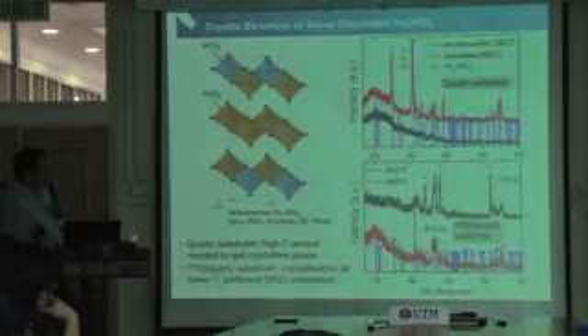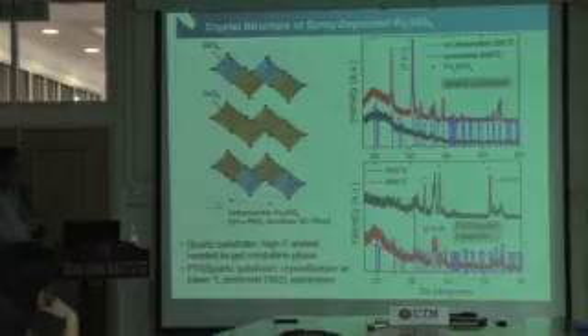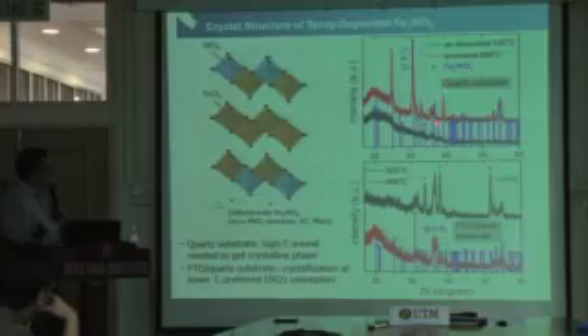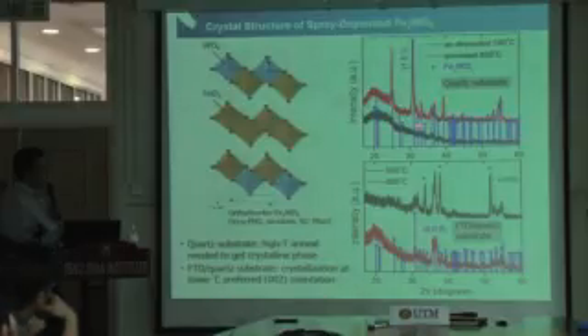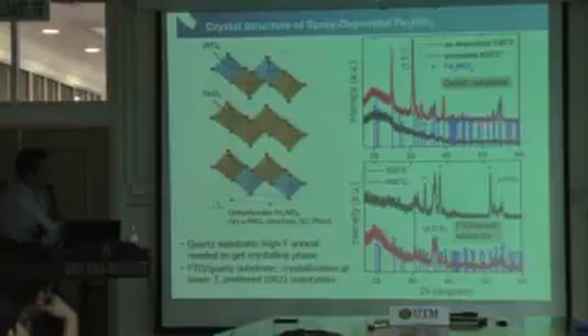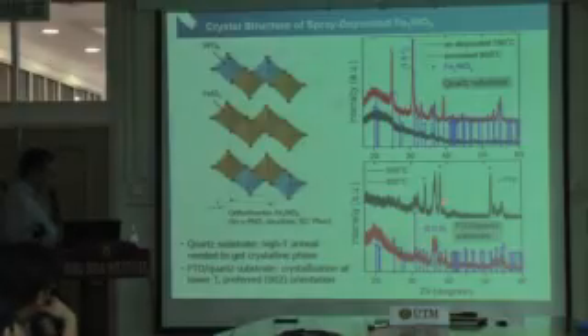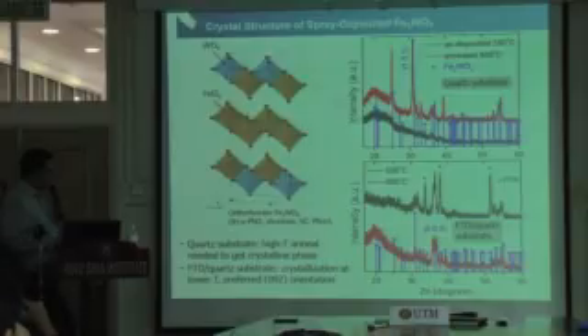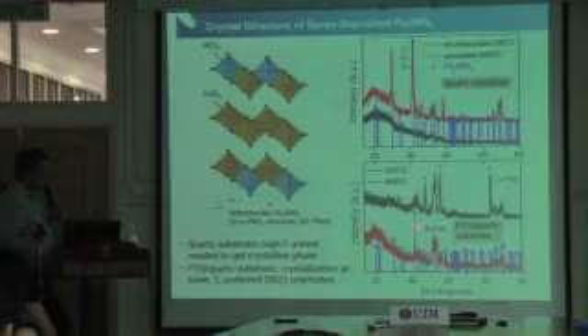And then we checked the crystal structure as deposited at 500 degrees C and annealed at 800 degrees C. It turns out that on a quartz substrate, we need a high-temperature anneal. Only when we anneal it at 800 degrees C do we start seeing the phase, whereas as deposited we see nothing. But on FTO, both as deposited at 500 and annealed, we already see some crystalline phase. So crystallization happens at a lower temperature when we deposit it on FTO, with a preferred 002 direction.